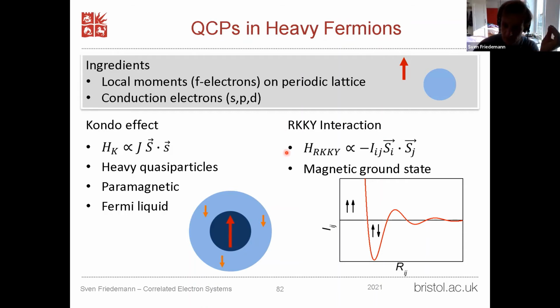So any magnetic interaction, so I made the point that a local moment placed at coordinate 0 in this sketch will have conduction electrons attempting to screen the local moment, but it won't manage over a certain distance. So in that range, a second local moment would orient parallel. It will then overscreen because of the sharp cutoff at the Fermi level, meaning that if you had a second local moment at this distance, it would couple antiferromagnetically. And an initial overscreening, of course, has immediately the consequence of further overscreenings, and hence these oscillations, such that you can have, again, ferromagnetic, antiferromagnetic, and so on.